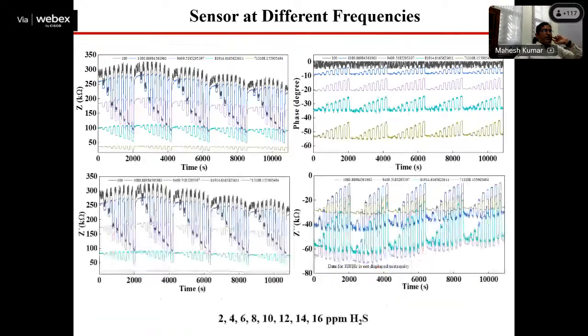So next, we have recorded all this data. We can consider the impedance here at 100 Hertz as a DC signal. After one cycle, second cycle, the baseline is not stable. Clearly we can see this from the black dotted data. This is at lower frequency, which means we are measuring only the resistance.